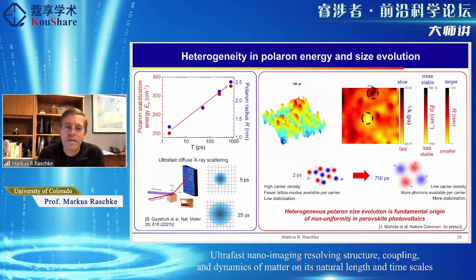And what we see is that there is this non-uniformity in this photophysical response, and this actually tells you, and is at least the most significant result, that in this empirical process by which the material chemistry is optimized, we are certainly nowhere near a physical limit of the optical and optoelectronic performance of perovskites. There is a lot of room for improvement if one could now optimize a cell where the local chemical composition of these structures is something where the entire system could be fabricated on.